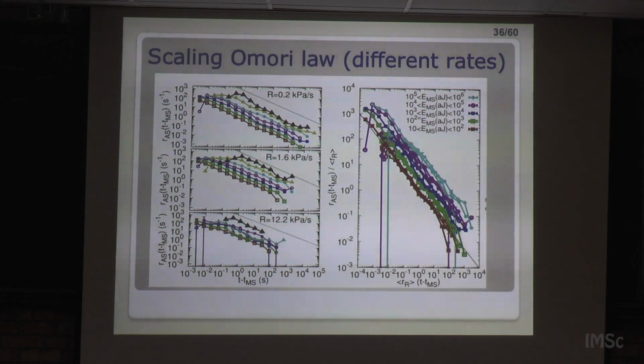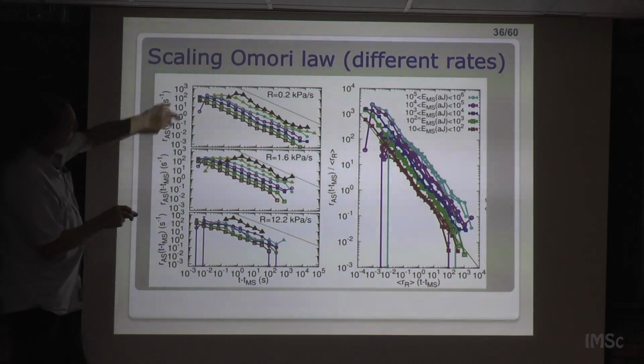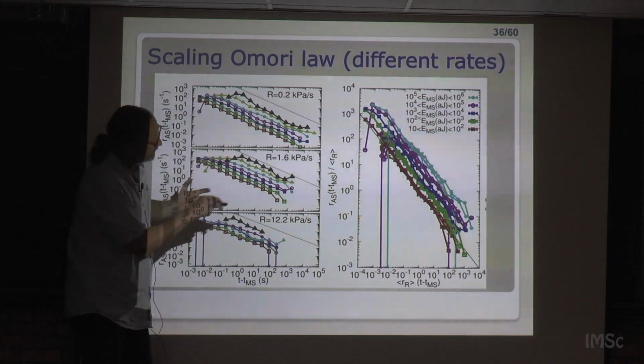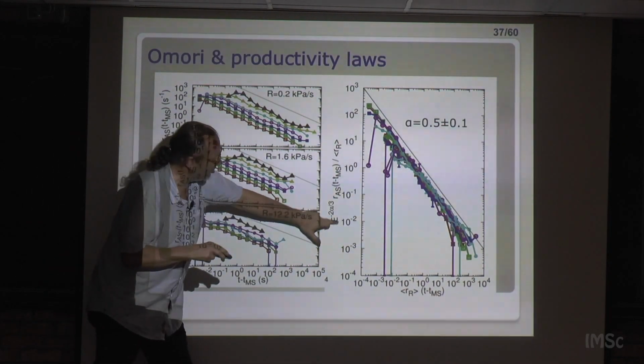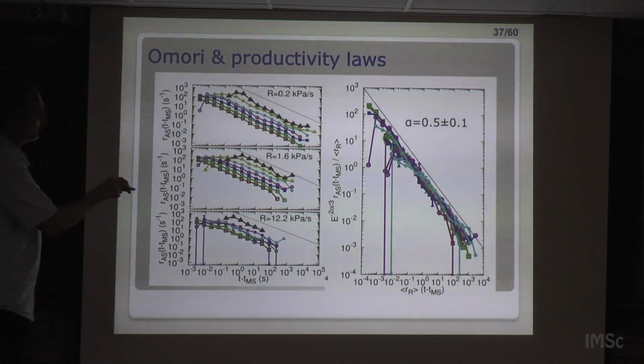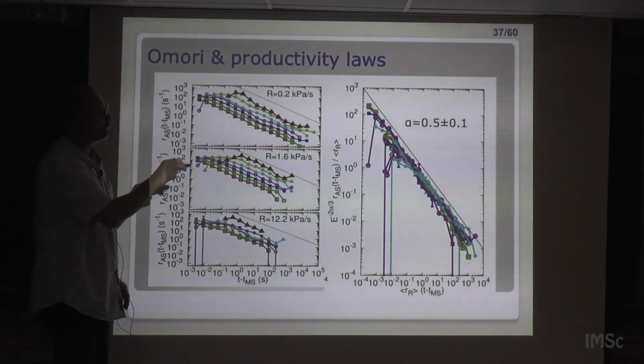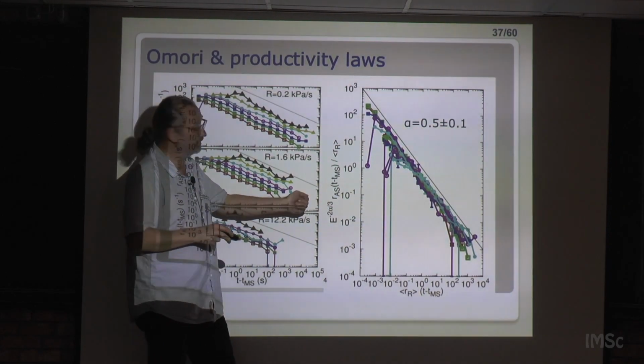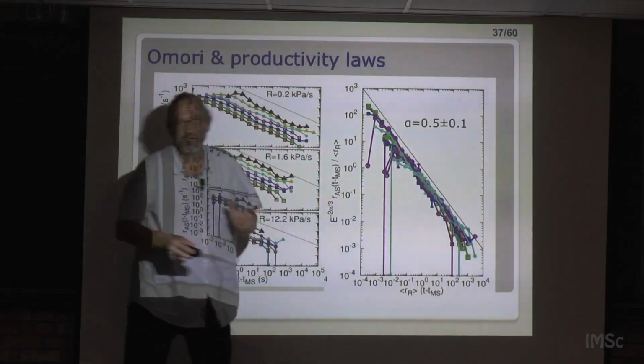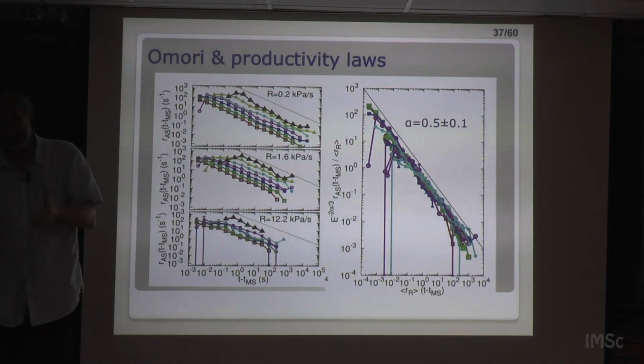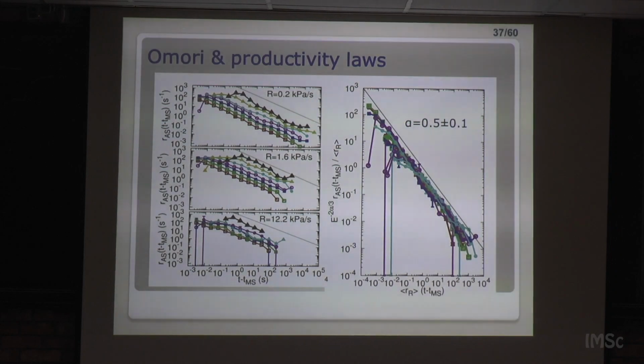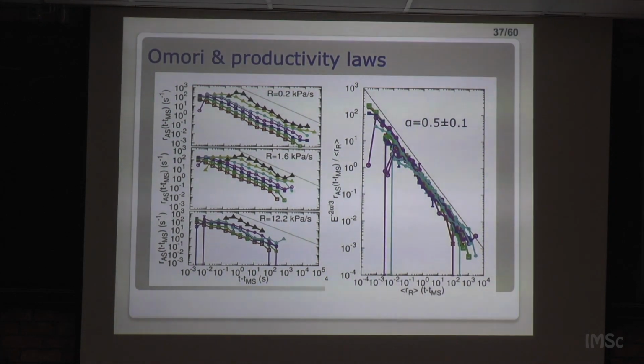But then when you scale, you go to what I proposed, the combined scaling. You first scale by the average rate, and you see that all the curves that have the same color overlap, and then you introduce here the productivity law, and then everything scales. And here you play with the exponent alpha until everything scales, and you deduce alpha. Also, the method of fitting alpha is the scaling. This also always has larger error bars than a method like maximum likelihood, but it's the way we have to fit alpha. So we get alpha and we get p from this scaling plot, okay?